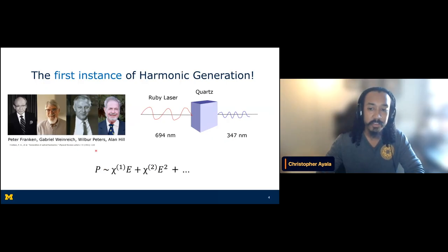What we have shown here is called the polarization equation, and this polarization equation just helps describe how a medium responds to an applied electric field. When you think about harmonic generation, we can describe this as a perturbative regime or a weak field, and it's characterized by a rapidly decreasing efficiency with increasing harmonic order, which means that the chi3 effects, chi4 effects, and so on are not taken into account because they are so weak in this case. That's why we see a second order effect.